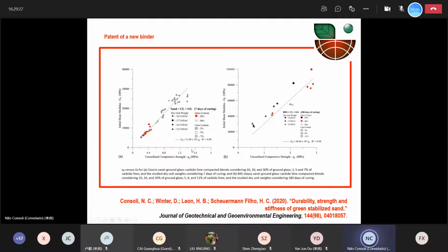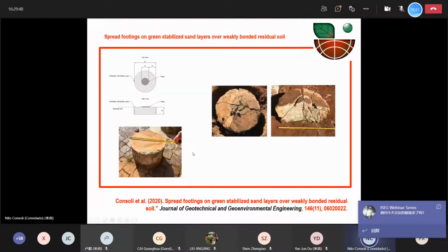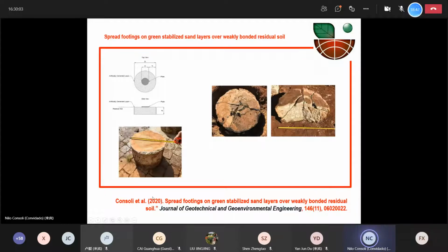Let's say in this case here about 1.5 megapascal. In this case here, we can even get 3 megapascal of unconfined compressive strength and some quite high initial shear modulus using this new cement that is based on residues. And here we went to the field and we have used this same cement to build some improved bases on which at the top we used to put some shallow footing. That was published in 2020, also at the Journal of Geotechnical and Geoenvironmental Engineering. So we call it a green cement, using it in the field to show how you can really improve.